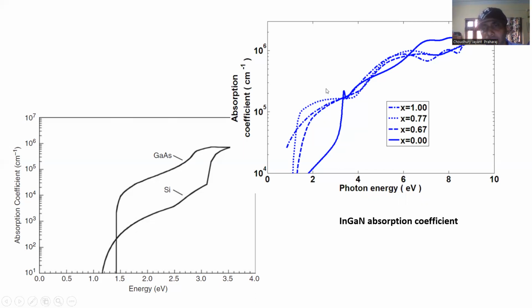And these absorption coefficients can be calculated, and also they can be measured. For example, there is the complex dielectric constant, which has a real and an imaginary part, and the absorption coefficient is related to the imaginary part of the complex dielectric constant or the complex dielectric function. And so we can have comparison between theory and experiment so that we can calibrate our band structure calculations to experiment also if needed. And we get fairly good agreement between experiment and theory for this kind of absorption coefficient.